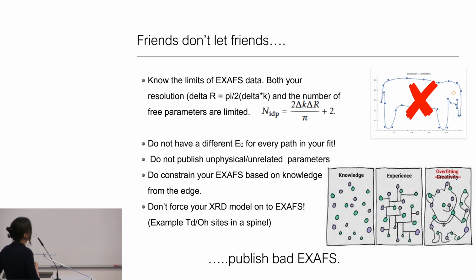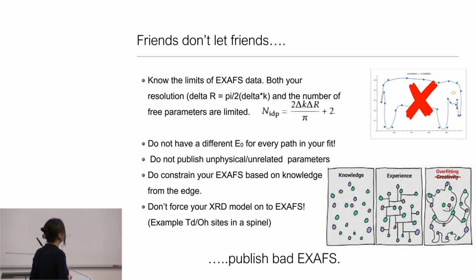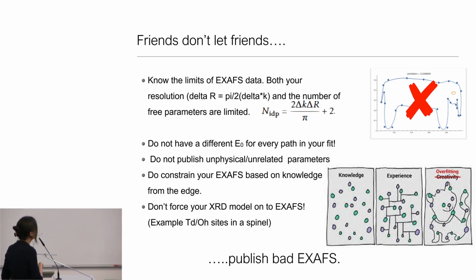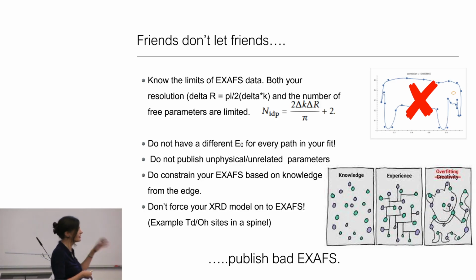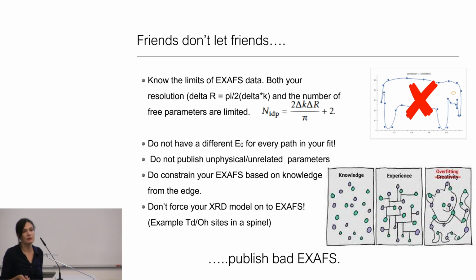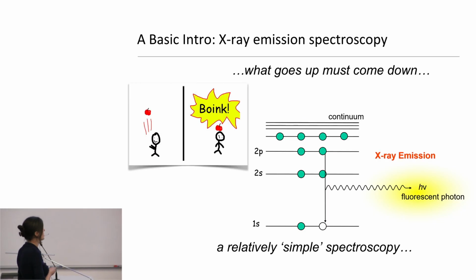Do constrain your EXAFS fit based on knowledge from the edge or knowledge from other spectroscopy. This is the whole holistic view that we're trying to discuss, that it's so important to put these constraints on it. And don't force your XRD model onto the EXAFS. There are some real overfitting examples where people try to say they have the freedom to separate out octahedral and tetrahedral sites. You can do that at the edge. They behave differently. But in a scattering-based picture, if you don't have the resolution, you don't have the resolution. And again, this is where maybe more sophisticated emission methods come in to separate that out. And so that's what we're going to switch gears to.